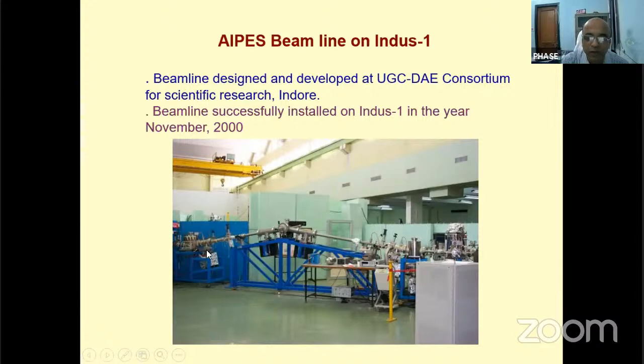You will see that all these are under metallic shielding or metallic pipeline, because the energy range we are talking about is the vacuum ultraviolet or soft X-ray. Vacuum ultraviolet or soft X-ray photon beam is naturally absorbed in air, so one cannot do this experiment in air. Just like in X-ray diffraction, hard X-ray is not absorbed in air, so we require lead shielding and other things. But the soft X-ray or vacuum ultraviolet beam does not travel in air, so a vacuum tube line is necessary. The whole line is covered.